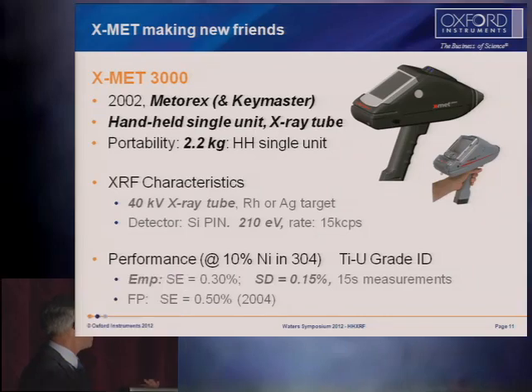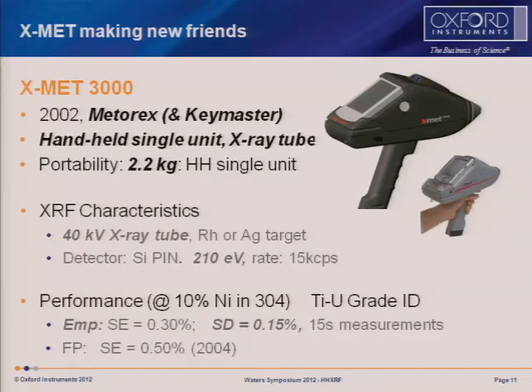So what did that do for results? Well, it got us down with a standard deviation now down to 0.15, really making good quality measurements. And for the first time now, in 2004 with the tube excitation, the fundamental parameters calculations were also added in to reduce the number of standards needed for real-life analysis.